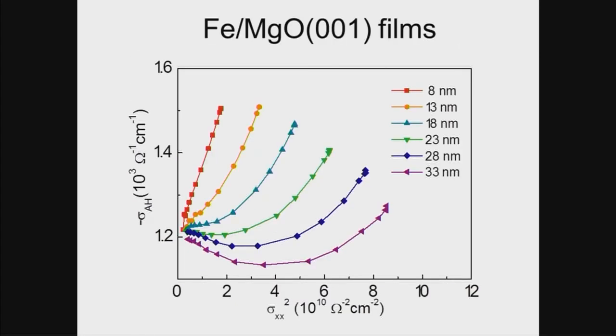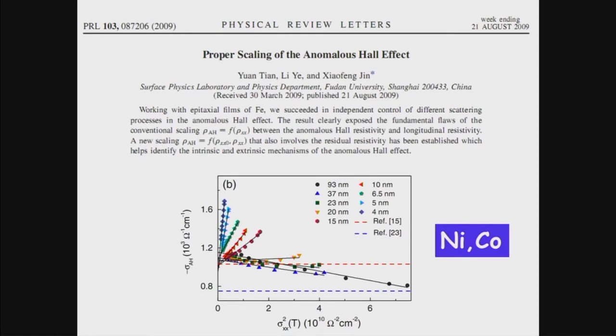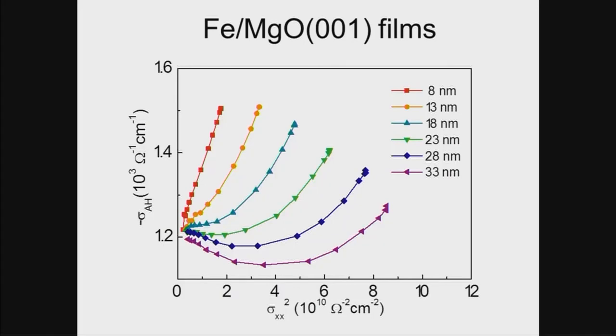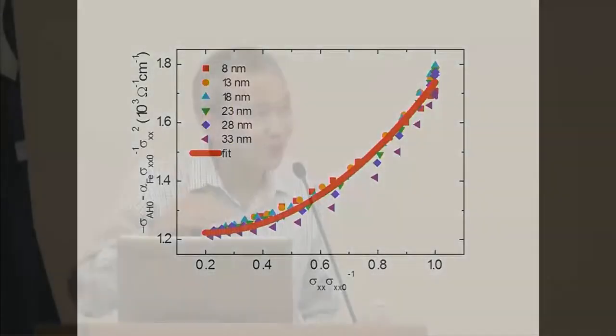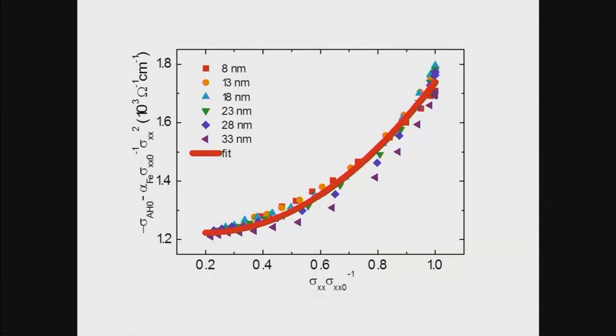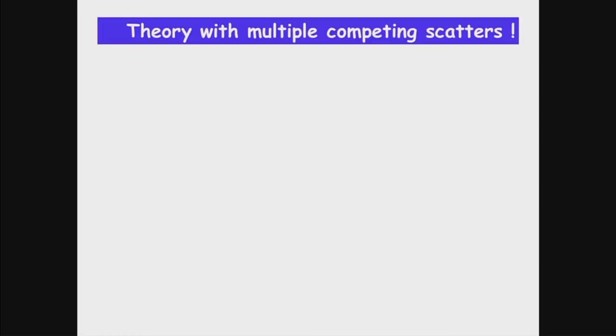When we published that paper, we already noticed in thicker film there's some curving happening. That was a little bit puzzling, and we did a better job with another system, a better high quality sample. So this curving is getting more and more significant. This is the point we started the collaboration with Professor Chen Yu. Once you treat the data, subtract the skew scattering, and plot sigma_xy over sigma_xx0, they all collapse on top of each other. So that means there's some universality within.